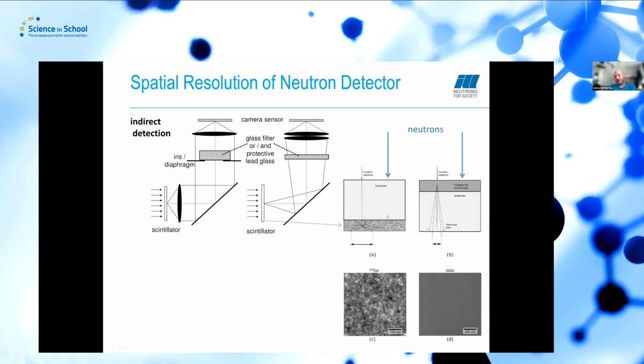And there are different approaches. So you could, for instance, say, okay, I deposit a powder screen on a substrate, and then if you look at the microstructure with a microscope, you see that there's inhomogeneous illumination of the camera sensor that can sometimes be a bit bothersome. Or you could have, for instance, a doped layer of a single crystal material, for instance produced by liquid phase epitaxy on a substrate. And this is the case here of the GGG crystal.